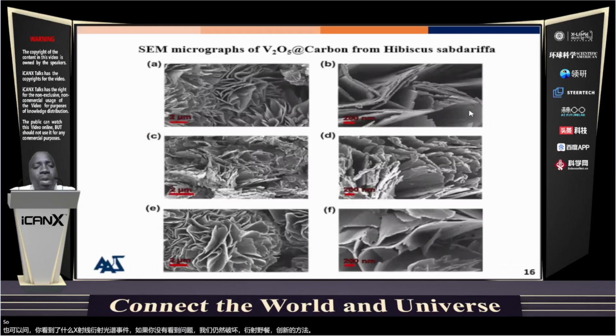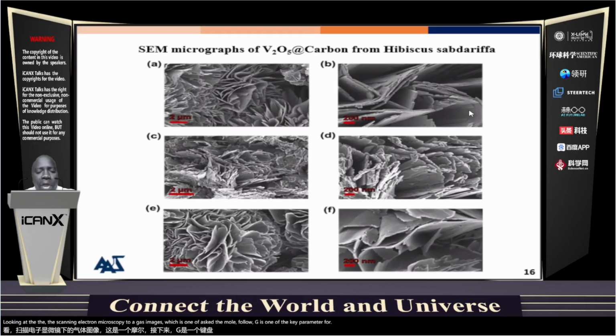Looking at the scanning electron microscopy images, morphology is one of the key parameters for energy storage applications, because the interaction between the electrolyte and the active material, the wettability, is one of the best parameters that control the efficiency of the energy storage of the device, of the electrode.